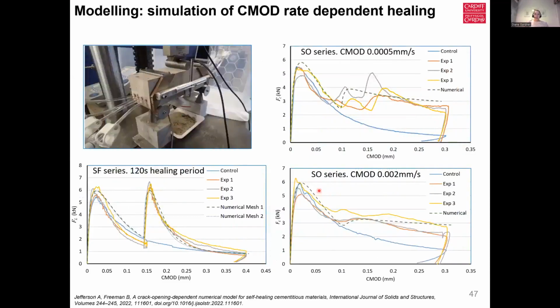So if you think back to some of the tests that I showed you earlier, the test results, I talked about using different CMODs and using different static crack periods, which would keep the crack open. And my colleagues tried their model that was simulating this, and I think you can agree we get quite good correlation in terms of being able to understand at a certain crack width, if we hold it open, we get flow of the healing material, we get regain of strength, and upon reloading again we can mimic the response that we see. And again, at different CMODs, you get the influence of the rate at which that healing agent is curing in that crack, that progression front of the curing, reflected in the response that we see here.